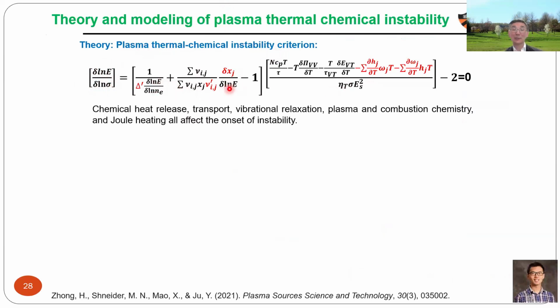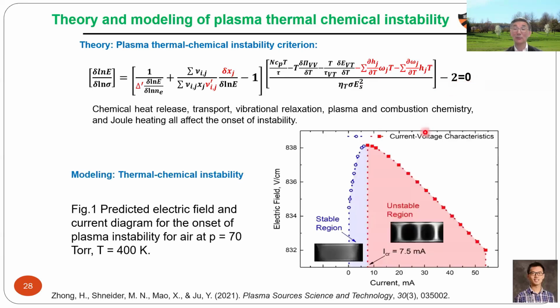It's governed by plasma chemistry and plasma energy. It's governed by the convection, vibration-translational relaxation, combustion rate, and combustion heat release, normalized by the Joule heating. If this is greater than 2, plasma will be unstable. If this is less than 2, plasma will be stable. So we did some computation and experimental verification. Indeed, looking at electric field as a function of current, if this criterion is greater than 2, plasma becomes unstable.